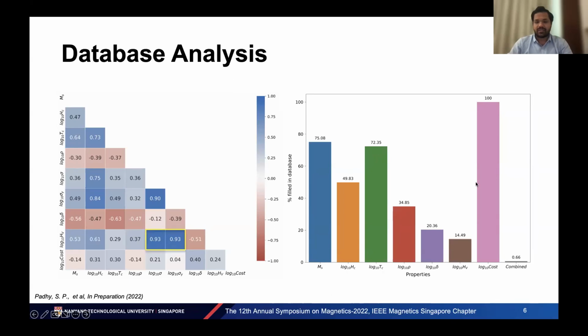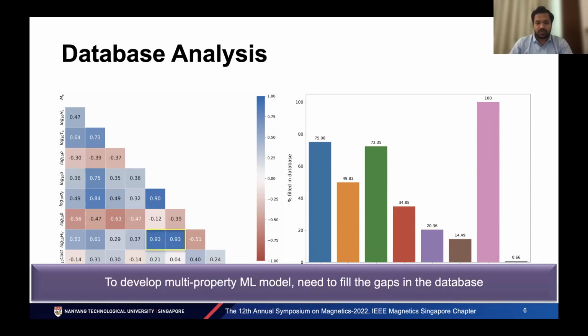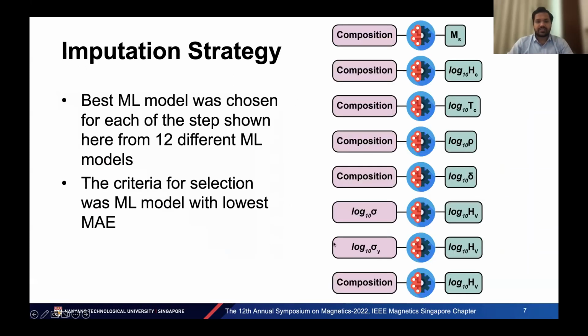Now, if we see the image on the left-hand side, we can see that MS and TC were the most widely studied properties, and HV was the least widely studied property. When we tried to find out how many compositions have all of the properties combined, we found that only 0.66% or 8 data entries were available in the database. Therefore, in order to design a new multi-property optimized alloy, we would need to fill the gaps in the database. For that, we developed a unique imputation strategy as shown in this figure, step by step.